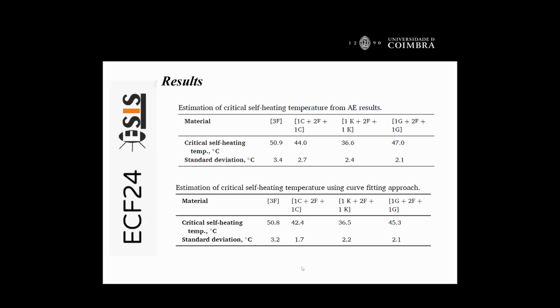These tables were based on the self-heating temperature and here on the acoustic emission. And we can observe, for example, for flax, that the value was 50.8, and for the acoustic emission it is 50.9, but it is inside the standard deviation. With this, we can say that this strategy proves that thermography is a very good indicator for the self-heating temperature, and we can estimate a critical self-heating temperature that we can prove with evidence from the acoustic emission.